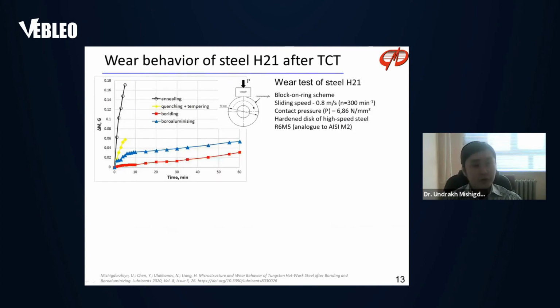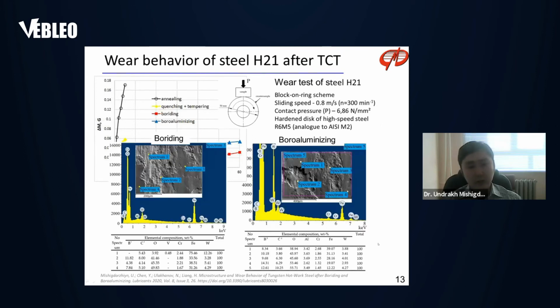Now, one of the crucial properties of a borided layer is wear resistance. This test was done according to the block-on-ring scheme, and the counterpart was hardened high-speed steel. It is clearly visible that both boriding and boroaluminizing resulted in enhancement of the wear resistance of H21 steel. However, the wear mechanism differs.